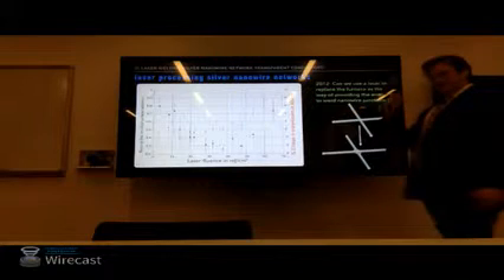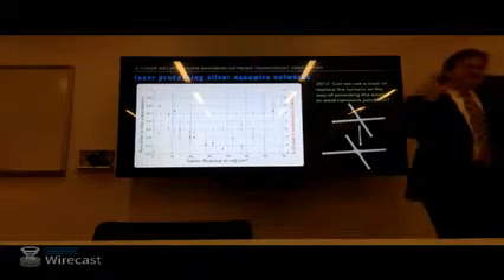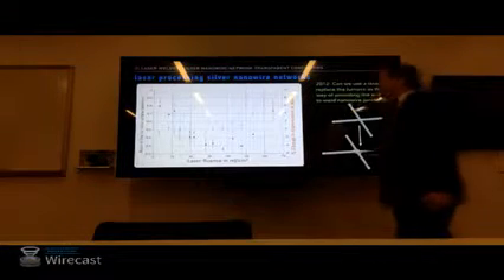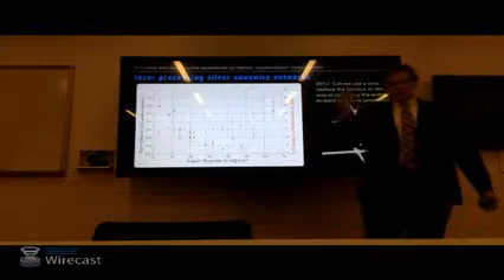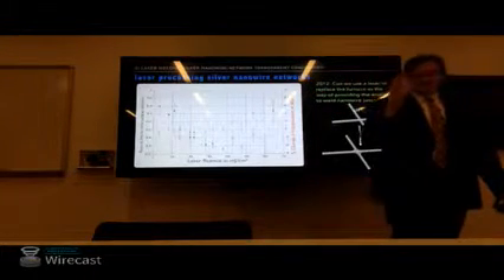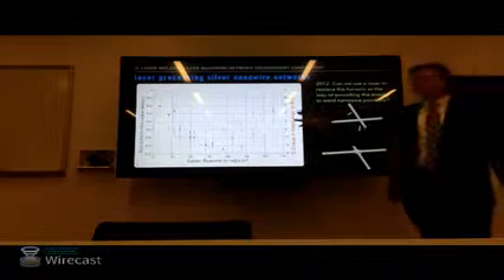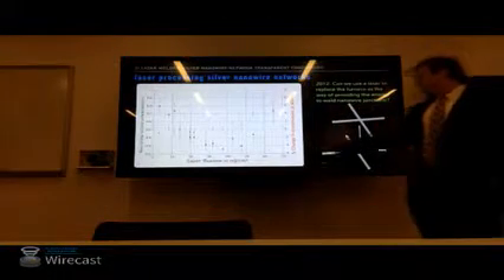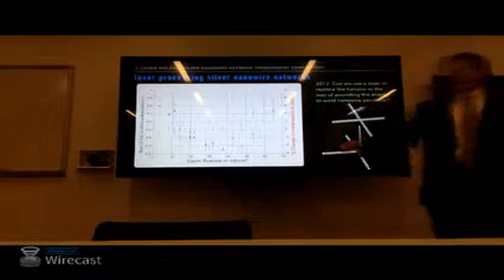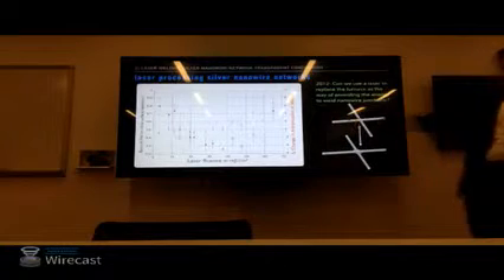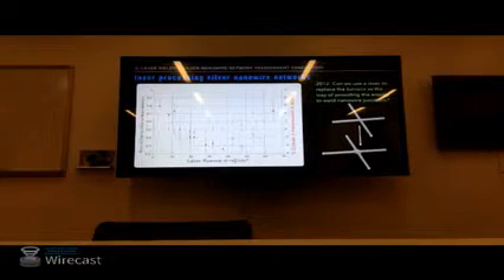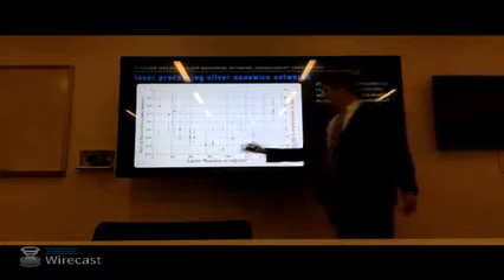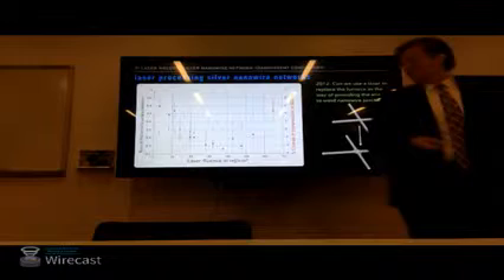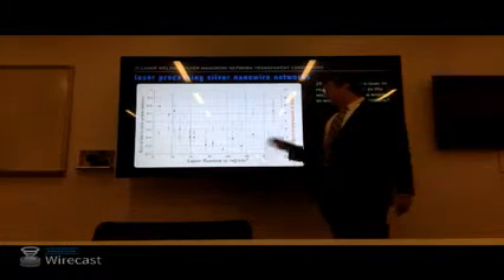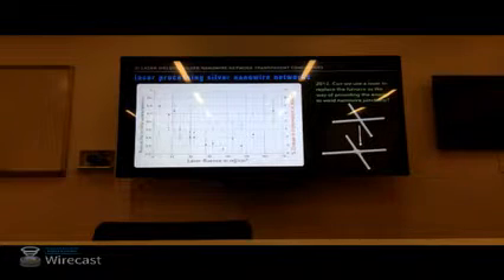So if we make a lot of nanowire networks, and in my 6 years, I don't even want to think about how many nanowire networks I've made, we go and we measure sheet resistance before, put it under the laser, and measure that same device, that same sample again. We can report a ratio of final to initial sheet resistance as a function of laser fluence. That's the energy density again. And now the black dots are that data set, the resistance data set. And what we see is we can have up to an 80% enhancement, so a final resistance that's 20% of the initial resistance, in an optimal processing range of maybe 20 to 50 millijoules per centimeter squared, which is actually a relatively low dosage of laser radiation.